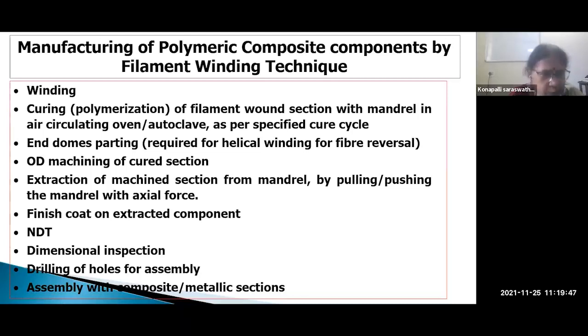Then OD requires us, you have to machine, because what happens in filament winding is constant volume of material deposition. So if your cross-section diameter is less, more volume, more thickness will be deposited. If your diameter is more, less material will be deposited. So here, basically, it is a near net shape component we get. So we have to machine a little bit. Of course, machining in composite is not advisable because we lose mechanical properties.